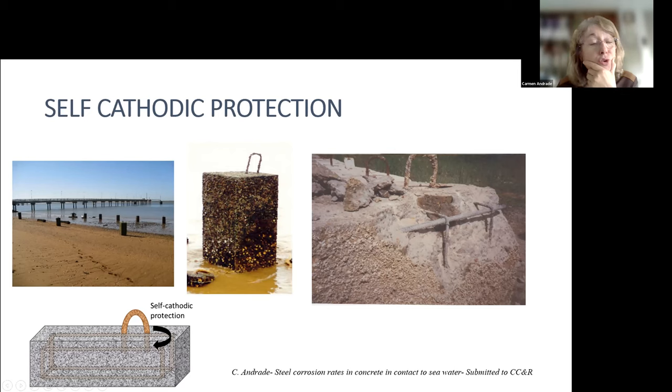We have these blocks, or we had these blocks in seawater in Spain that had this hook. This is going to be published in Cement and Concrete Research. Near this hook they are now about 30 years old, and they are completely contaminated with chloride. They are 50 centimeters and two meters. And the point is that when you open them, the bars are completely clean because this external hook is acting as cathodic protection. And this is a very simple and direct manner to protect the concrete.